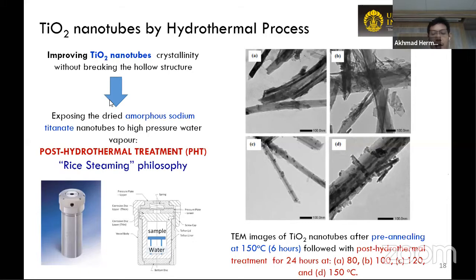We can see from the TEM image the sample after pre-annealing at 150 degrees Celsius followed by post-hydrothermal treatment. So this is the example that before we subject the nanotubes to the post-hydrothermal treatment, we need to do pre-annealing at 150 degrees Celsius. Why? Because we realize that the high pressure of the water vapor during the autoclave post-hydrothermal treatment can make the structure collapse.